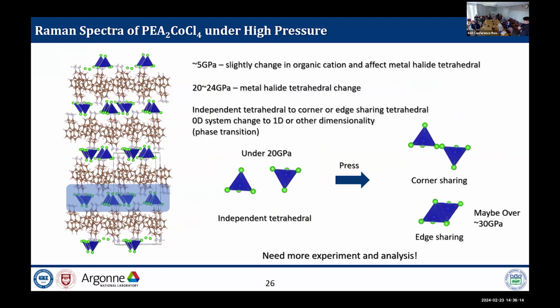So I think there is some tetrahedral changing phase transition in this structure. Under 20 gigapascal, there are just independent tetrahedra. Near 5 gigapascal there is a phase transition, but not much effect on the tetrahedra, just some change in the organic and inorganic chemical bonding. When pressing up to 20 gigapascal, it seems there is some change in the tetrahedral system, such as independent tetrahedra to corner-sharing tetrahedra or edge-sharing tetrahedra, which can affect the structural dimension, zero dimensional to one dimensional or other dimensions. So there is a change in the orbital configuration and photoluminescence is measured. This is just one possible explanation, but I'm not sure. So we need more measurements using Raman spectroscopy, XRD, or other methods.